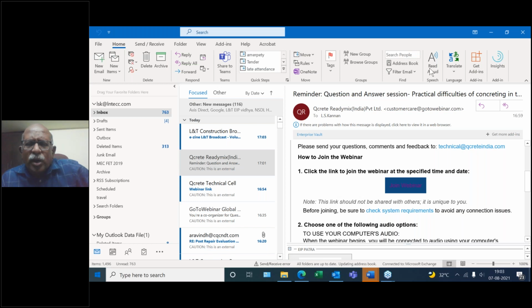Whatever we are talking about, FCK plus 1.65S is only for the laboratory strength. It is not for field strength. Field strength has to satisfy only FCK. Even if you refer to that, it is for a cube, not the NDT part of it. Suppose you are taking a core, you have to refer only to 25, that is FCK, and not to your target strength. Even if you refer to IS 456, what it says is the concrete is accepted based on 28 days results, as stipulated as per table 2.